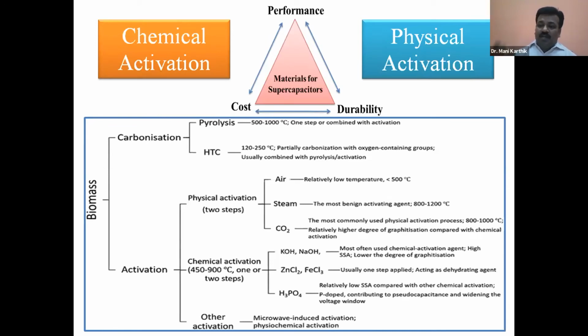Physical activation generally starts with already purified carbon. That's why I told you, if you convert biomass into carbon, that carbon should be 100% pure. Then only that pure carbon, with physical activation using air or steam or CO2, can be converted to porous carbon. Then that is useful because you can eliminate any other washing steps. So that kind of carbon is economically viable. That's the reason steam activated, and some people using both steam and CO2 activated compound, is a well commercialized sample. You can go for large quantities.